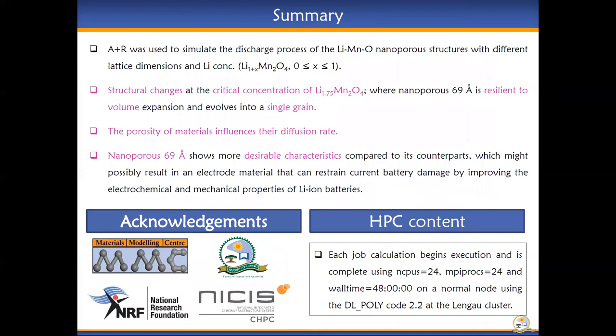In summary, the amorphization and recrystallization technique was used to simulate the discharge process of the Li-Mn2O4 nanoporous structures with different lattice dimensions and concentrations. Structural changes at the critical concentration of Li1.75, where nanoporous 69 Å is resilient to volume expansion and evolved into a single grain, was observed.